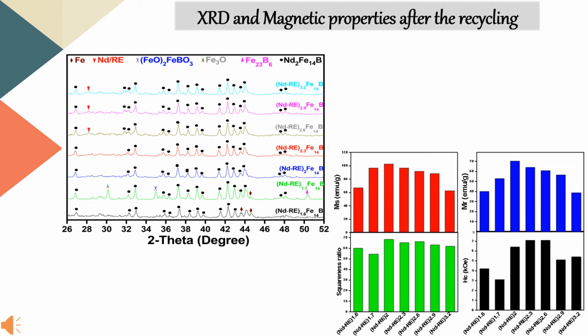Here we got the 7 XRD graphs, and similarly the 7 different MPMS data sets. We didn't show the magnetic hysteresis loop here, but in the paper that's available. We extracted some results from the hysteresis loop for the squareness ratio, MS, MR and coercivity. From the MPMS data, as far as the MR value is concerned, NdRe2 is the best composition. If we talk about coercivity, then of course NdRe2.3 or 2.6 is the best one for overall magnetic properties. So NdRe2 is a good composition.